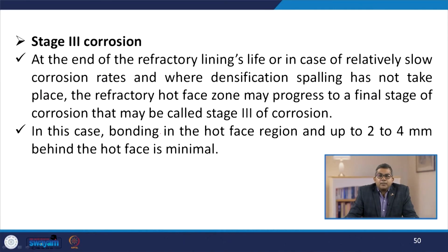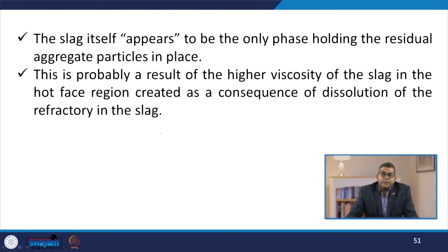Let us have a brief outlook on stage 3 corrosion. At the end of the refractory lining's life, or in case of relatively slow corrosion rates, where densification spalling has not taken place, the refractory hot face zone may progress to a final stage of corrosion that may be called stage 3 corrosion. In this case, the bonding in the hot face region, and up to say 2 to 4 mm behind the hot face, is minimal.